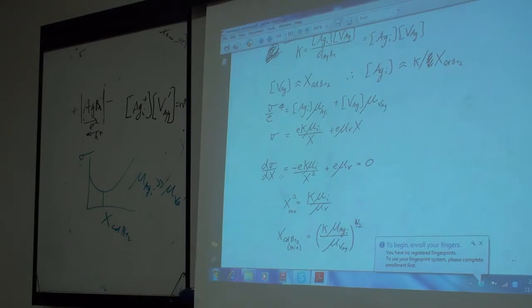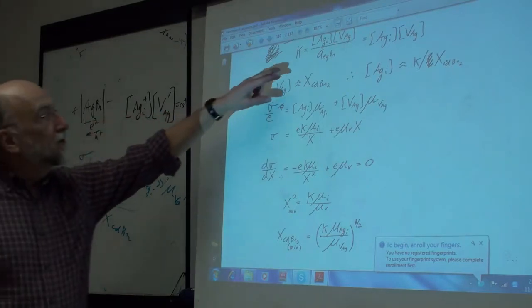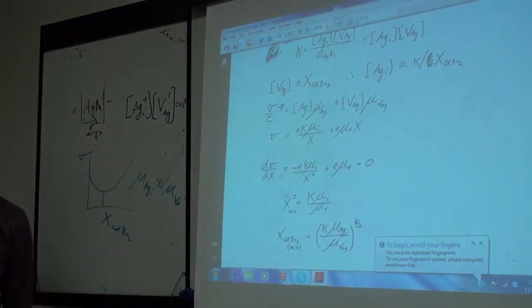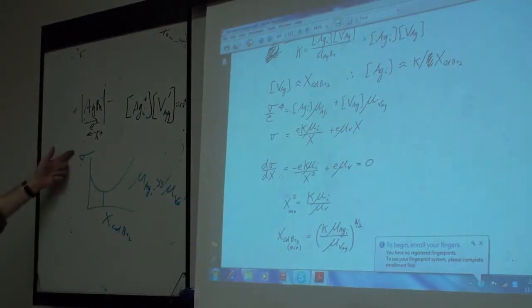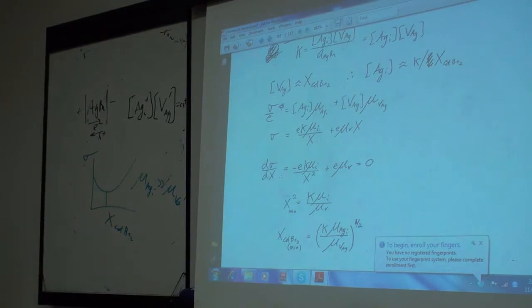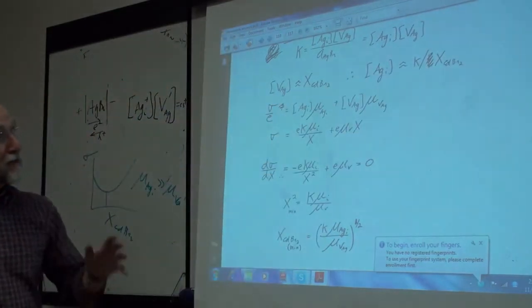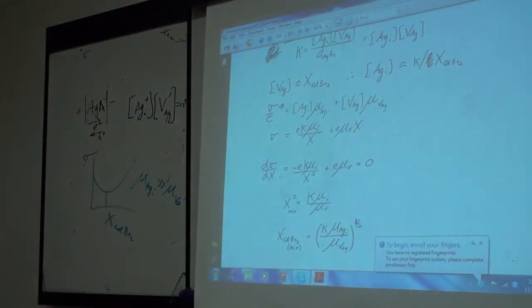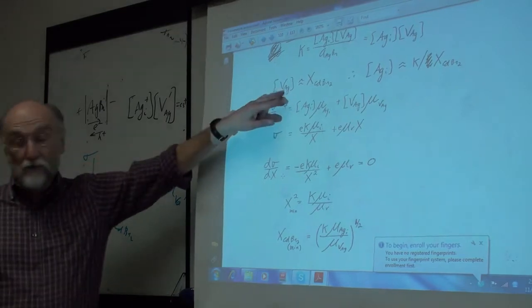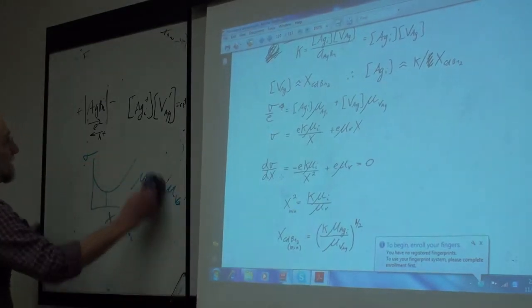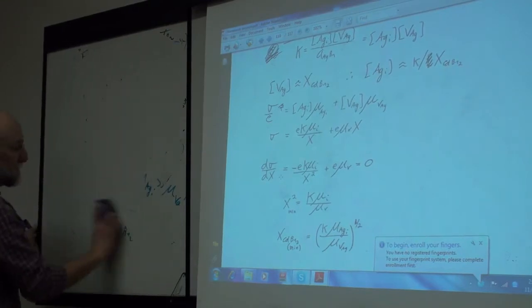And this is called extrinsic, these are intrinsic. The vacancies in pure silver bromide are intrinsic vacancies, which are caused only by thermal excitation: a silver ion simply popping out of its lattice site, forming a vacancy and an interstitial. The extrinsic concentration is given by actually adding a dopant, and every time you add the dopant, you just introduce the thing here. Okay, and then this is completely analogous to your semiconductors.